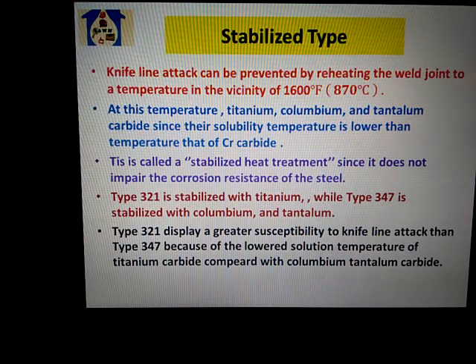Type 321 is stabilized with titanium, while type 347 is stabilized with columbium and tantalum. Type 321 displays a greater susceptibility to knife-line attack than type 347 because of the lower solution temperature of titanium carbide compared with columbium tantalum carbide.